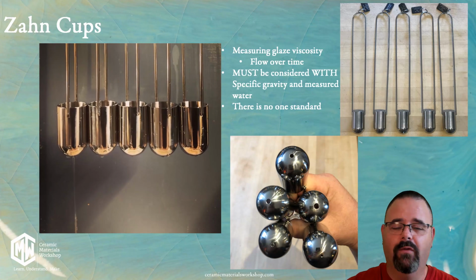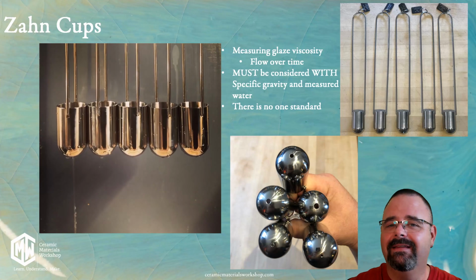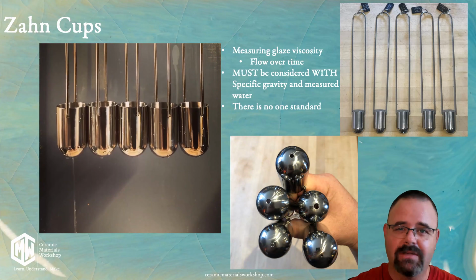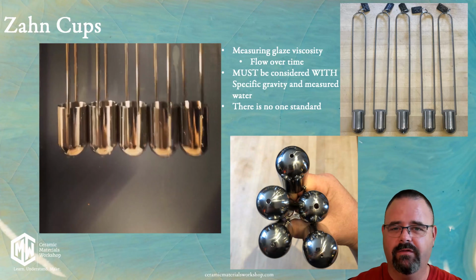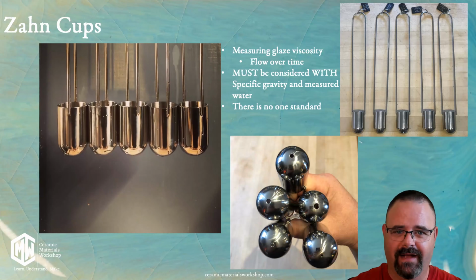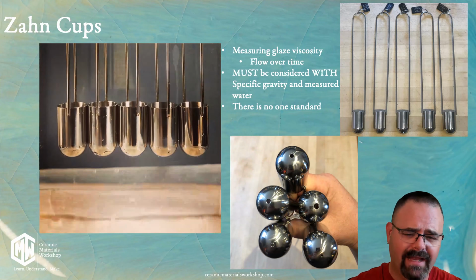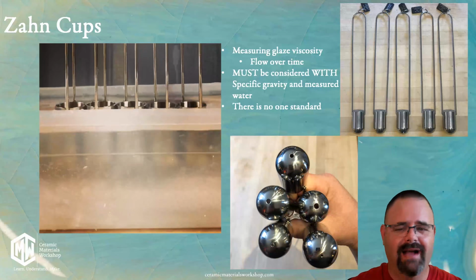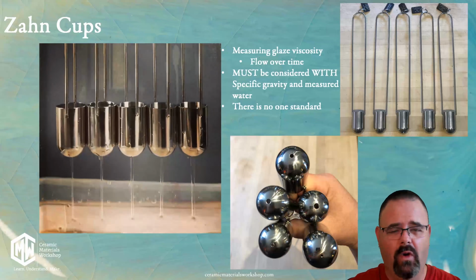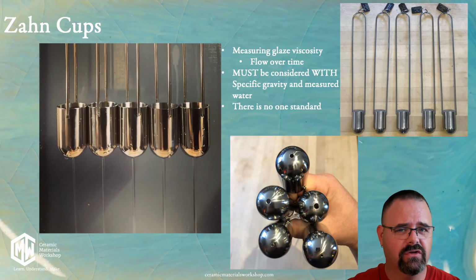One thing to watch out for of things being off is that some glazes need time to age. About 3 days is what you want to look for, and then they will shift their viscosity in that time. But if you combine a viscosity measurement with specific gravity, with measured water, you should have pretty good control over your glaze.